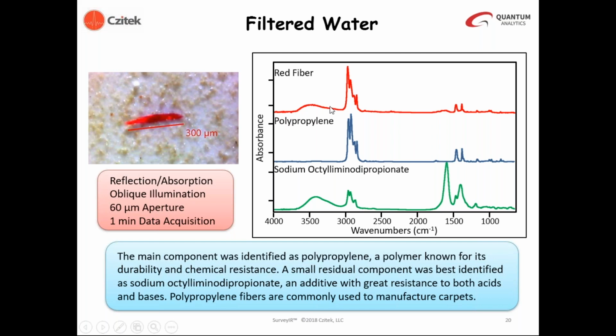So the spectrum of the fiber that we observe is shown on the top, and we could very simply identify the bulk of the material as polypropylene. A reference spectrum of polypropylene is shown in the middle. But we're also able to identify another component, sodium octyl iminodipropionate, and this is an additive that has great resistance to acids and bases. And polypropylene has many applications in engineered plastics, but some typical ones are specialized water bottles as well as fibers to manufacture carpets. Because of the shape of this material, it could be that this is a carpet fiber.